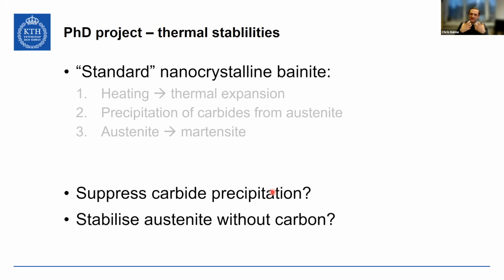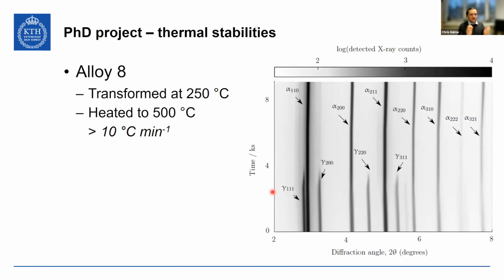Okay, so if we look at how they performed, this is alloy 8, and we did this at DESY, one of the experiments we took samples to DESY for. And as you can see, hopefully, the peaks associated with all of the phases, austenite and ferrite, begin to get lower in angle as the experimental time goes on.